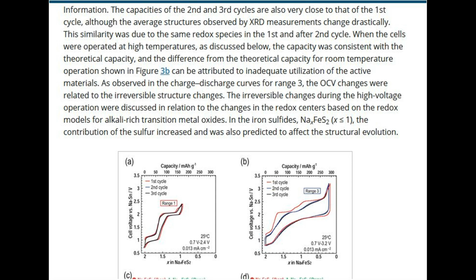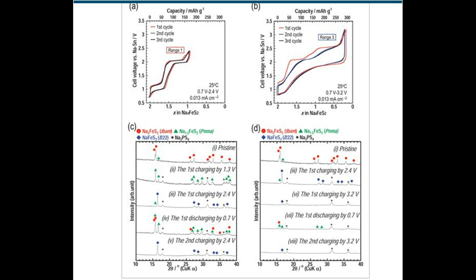As observed in the charge-discharge curves for range 3, the OCV changes were related to the irreversible structure changes. The irreversible changes during the high-voltage operation were discussed in relation to the changes in the redox centers based on the redox models for alkali-rich transition metal oxides. In the iron sulfides, NaxFeS2, x<1, the contribution of the sulfur increased and was also predicted to affect the structural evolution. Figure 3.